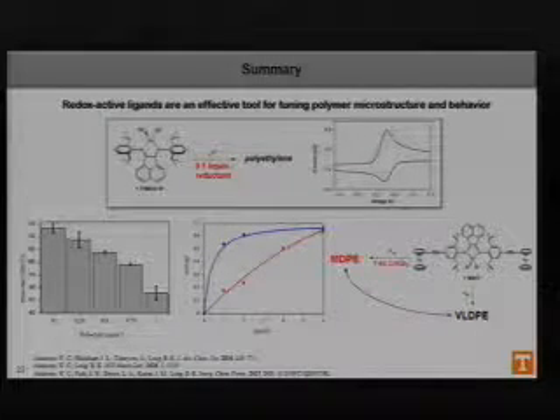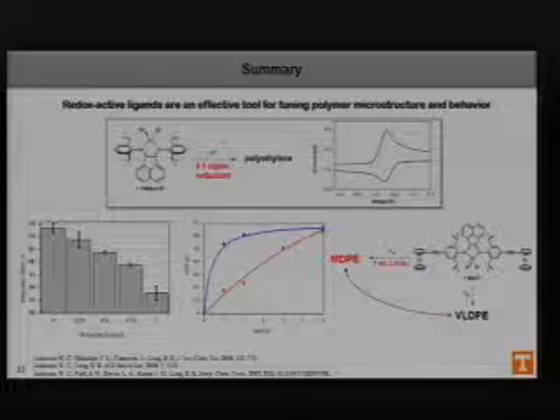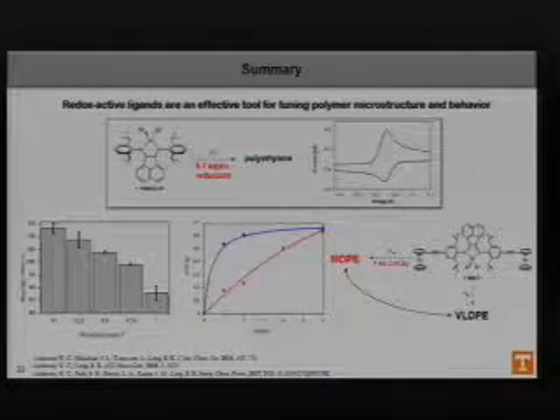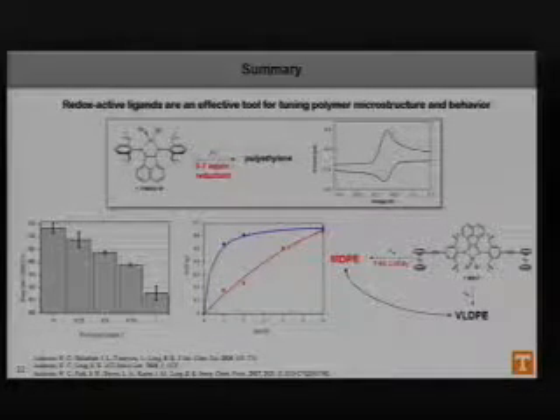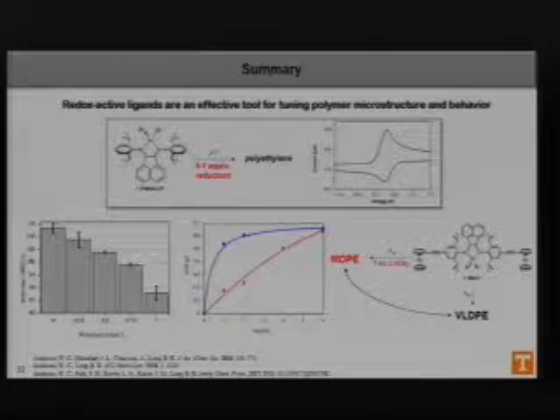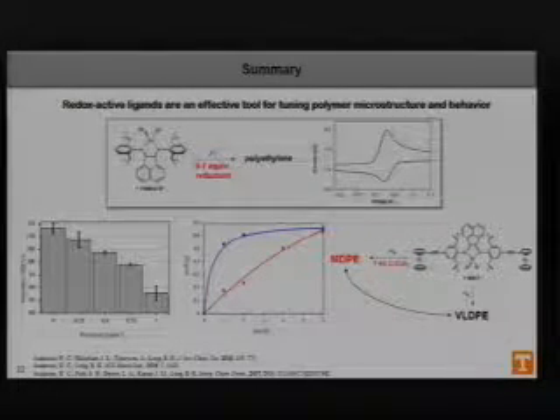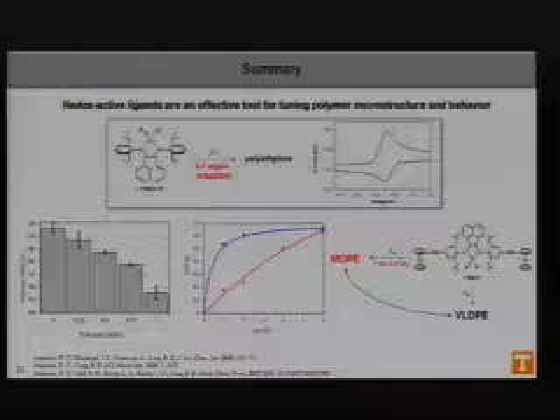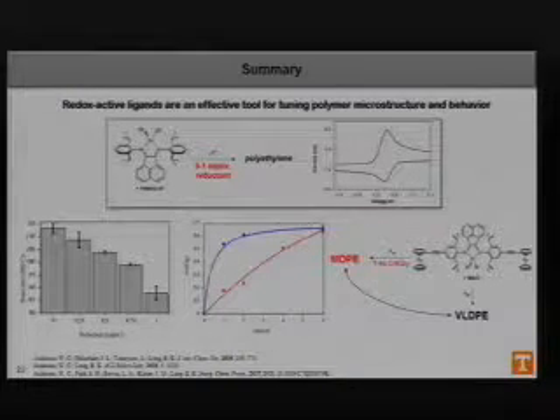So to sum all this up, redox active ligands are a fairly effective tool for tuning polymer microstructure and even controlling their branching content, the polymerization rates for larger olefins, and they can be used to even modulate polyethylene density as well.